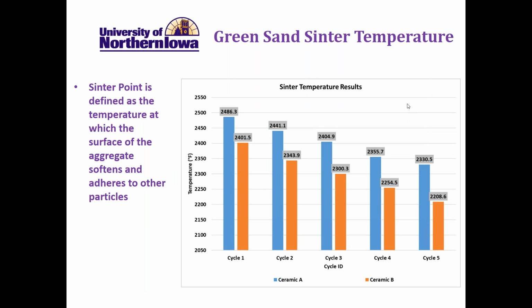When we look at the sinter points of these 2 materials, we can see that the domestic product, ceramic A, had over 120 degrees higher sinter point after 5 cycles. Now the cycles include mixing the sand, mulling the sand with bentonite, producing castings, shaking those castings out, and having a proportion wet reclaimed back to new.